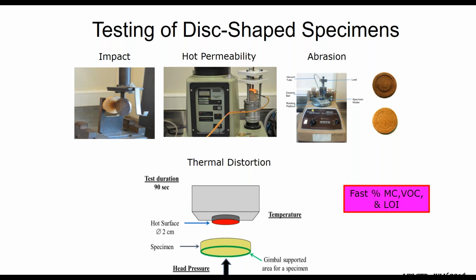All of these tests are dynamic in nature. What we mean by that, there are multiple properties that we run off of them. For example, in the simple impact for mechanical properties, we could understand the impact properties before the specimen sees elevated temperature and after elevated temperature, so that we could understand the mechanics in shakeout or retained strength. We can look at ambient to hot venting characteristics.